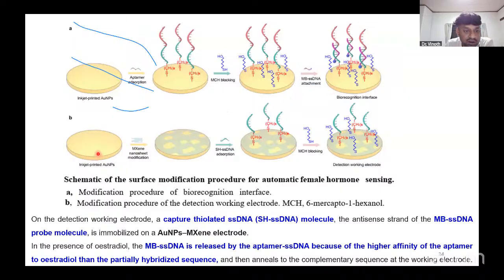And also here, inkjet printed gold nanoparticles with MXene, and then thiolated aptamer adsorption, which forms the Au-S bond, similar to the MCH blocking. This is used as the working electrode. For detection, the thiolated DNA molecule and antisense strand with methylene blue standard DNA probe molecule are immobilized on the gold nanoparticle MXene electrode. In the presence of estradiol, the aptamer has a higher affinity towards the estradiol than the partially hybridized sequence.